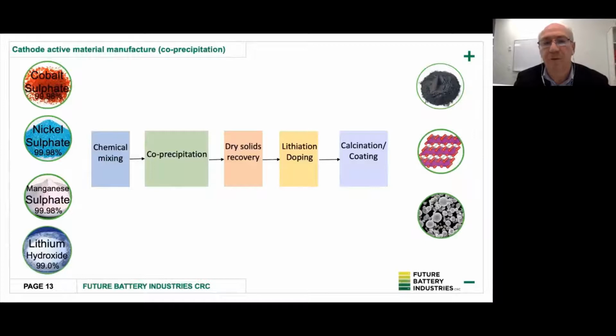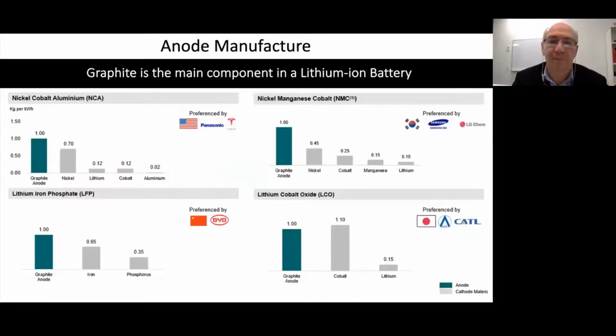Okay, so we've got our precursor materials. We want to form them into a single compound, and the process which we would use would be co-precipitation. To do that, we mix our precursors, we precipitate the materials with hydroxide materials so that we get a hydroxide precursor, which we then dry and recover the solids. The lithium's added as a dry material, which is mixed in and then furnaced and calcined and coated to produce the final material. So that process is being undertaken through collaboration with Australian companies and the Future Battery Industry CRC, here in Australia and in Perth.